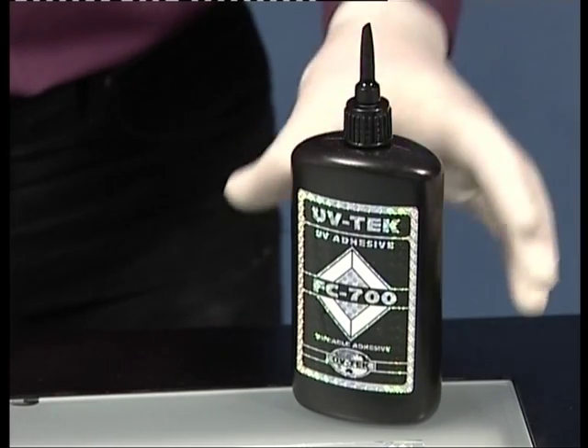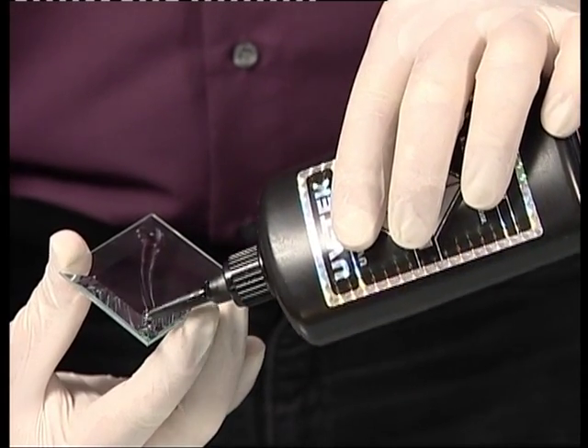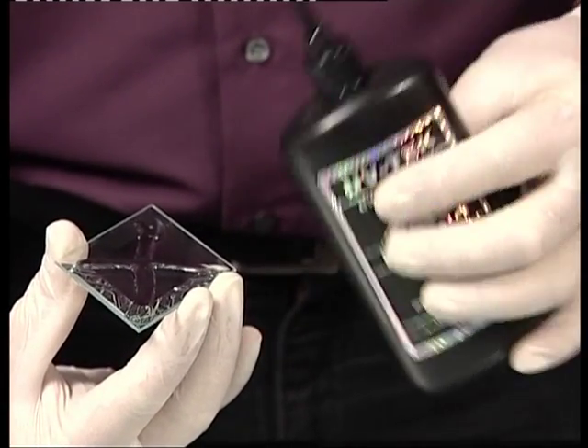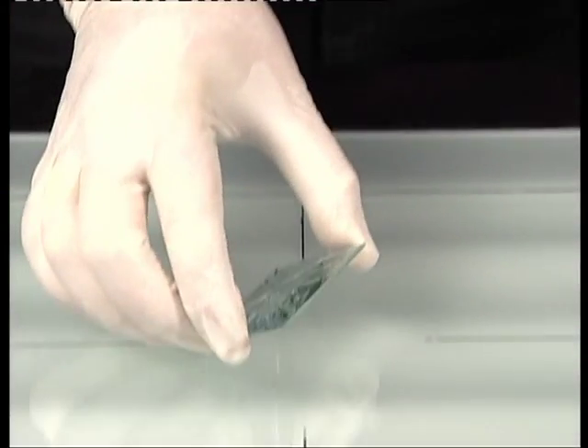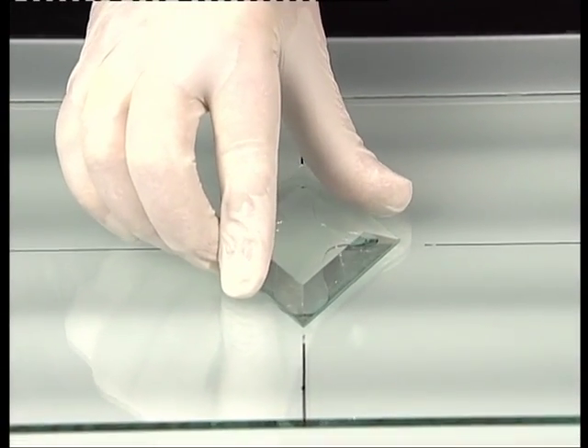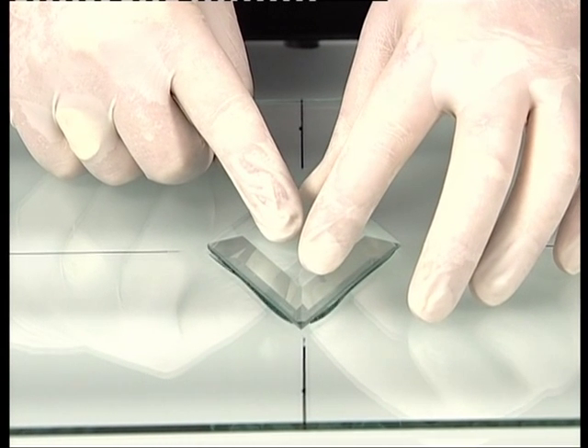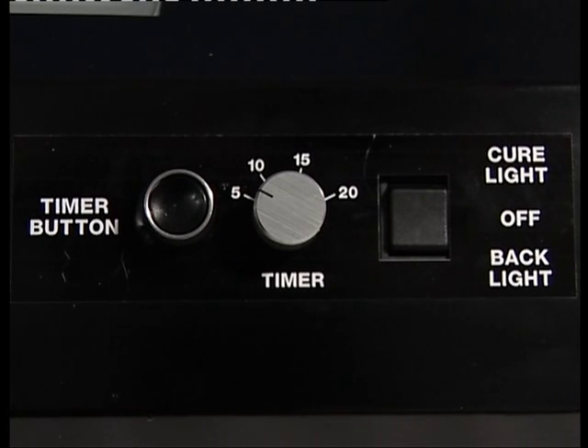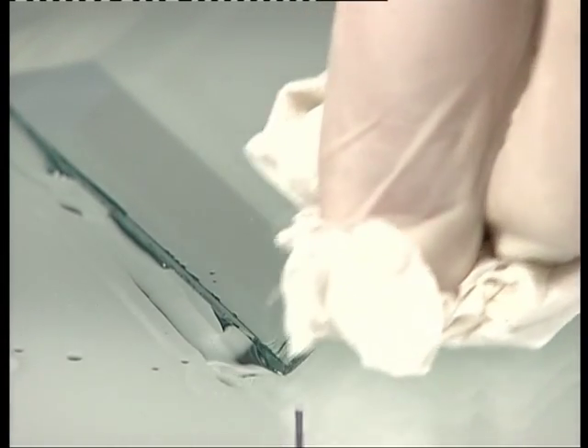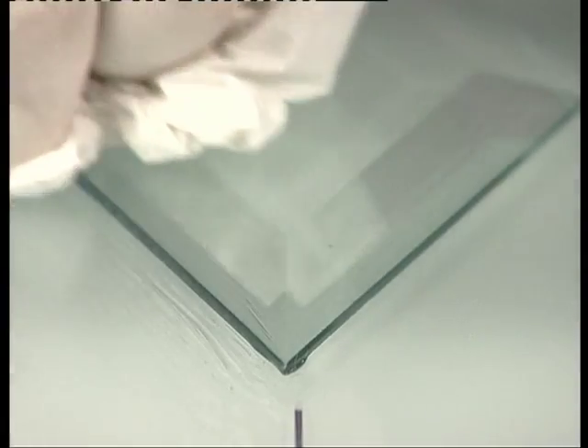FC700 is our rapid cure wipeable clear adhesive, ideal for volume bevel bonding. To part cure FC700, set the timer to approximately 5 seconds. Ensure the bevel is secure. Wipe away the excess adhesive. No knives, just wipe. Fully cure for a further 6 seconds and clean as required.